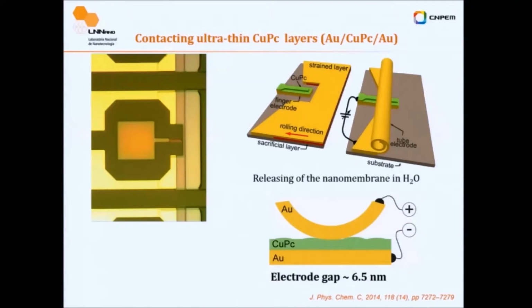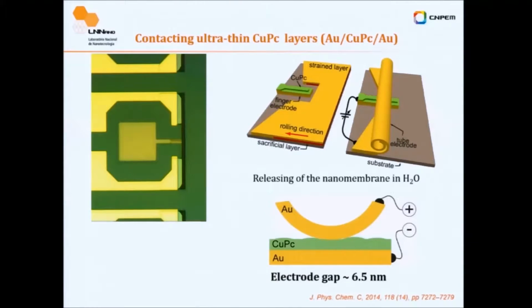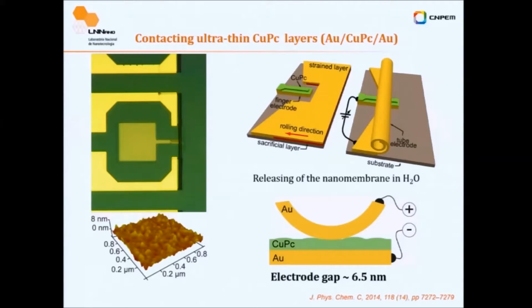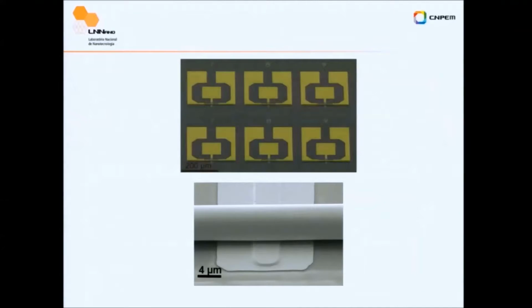So how does this work? You can see that this is the strained layer. This is my finger. I start to roll the system, the tube forms, and in the end it lies on top of my layer. Here is how the surface looks after I remove the tube. Basically, I have a micro roller that also planarizes the film. So a few devices on the surface, and a zoom in this region.